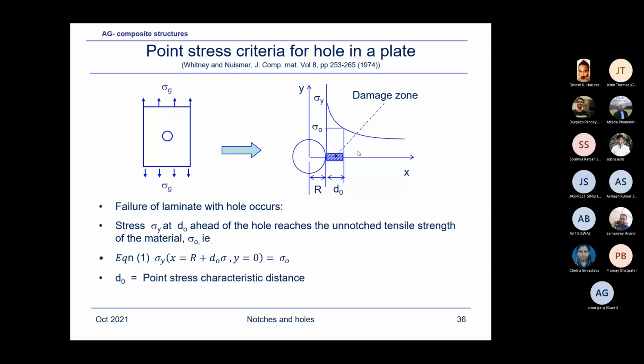What is the reason? They found that after fatigue cycling at smaller stress levels, damage around the hole edge occurred. So a small damage developed, as I've shown in the qualitative pictures in my slides, which then led to a reduction in the stress concentration factor and led to an increase in the residual strength. So that is the effect of the damage. They modeled based on that, calling it inherent flaw modeling, and they used Bowie's solution to determine the residual strength.